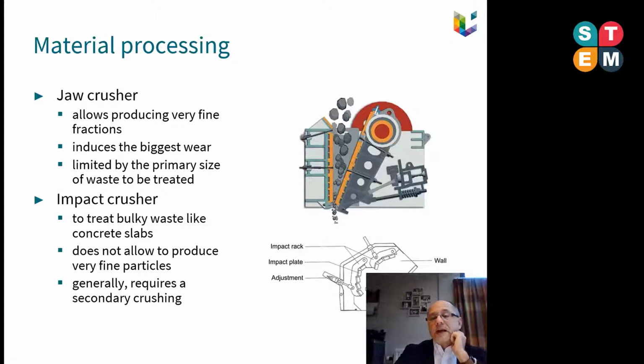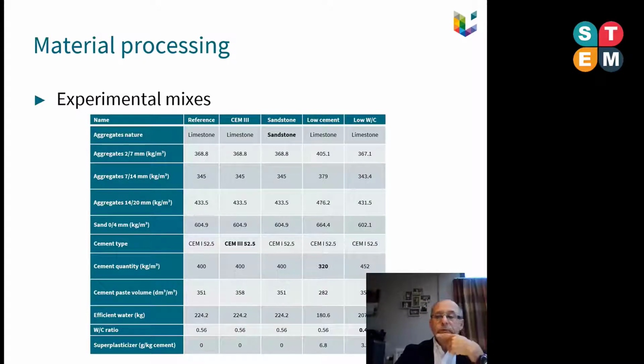How important is it to select the proper crusher? This is important from the point of view of the characteristics and specifically the flakiness of the material. Here you can see that we produce experimental mixes, changing for one reference concrete mix the type of cement, the type of material from CEM I to CEM III, sandstones and not limestone. We also change the cement content and the water to cement ratio. And we wanted to investigate the effect of crushing on the characteristics of material.